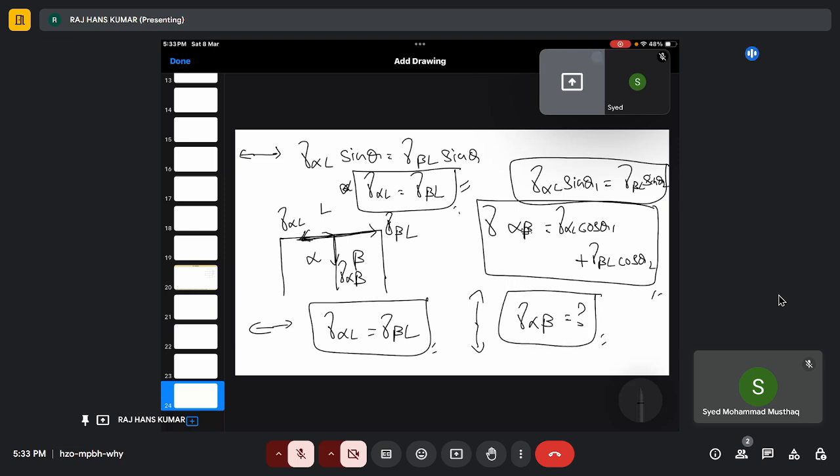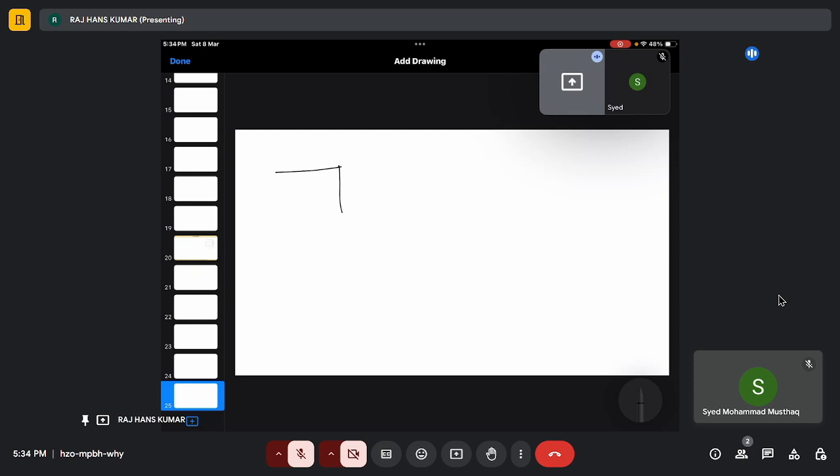Right? So there is no balancing here. So that's why there is a non-equilibrium condition in the planar interface. So that is the reason why, if for some unforeseen circumstances there is a formation of a planar interface, gamma alpha beta, gamma alpha L, gamma beta L, then because of this non-balancing force, this will drag this surface